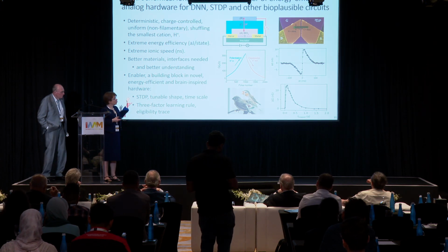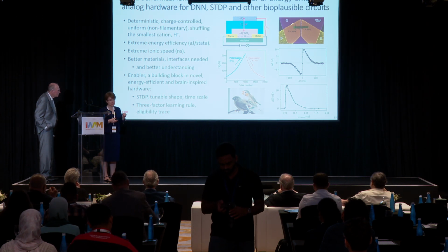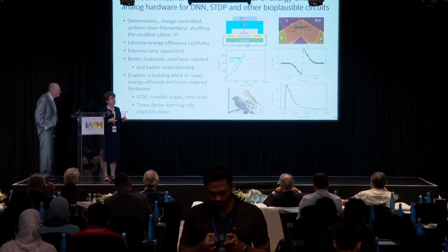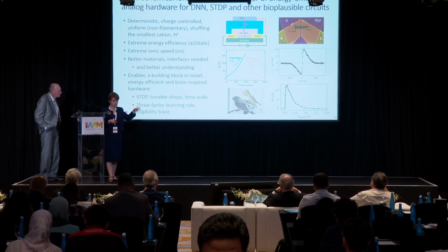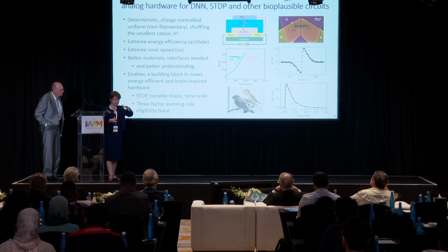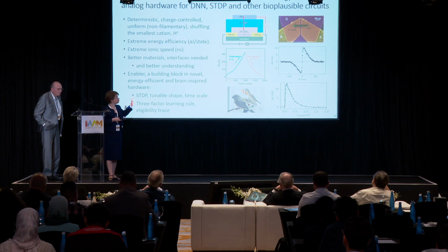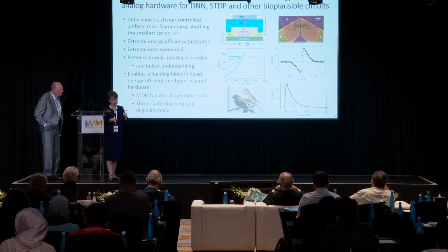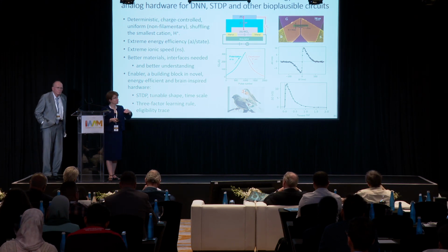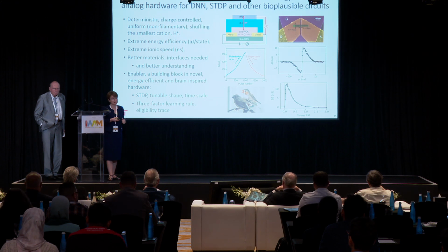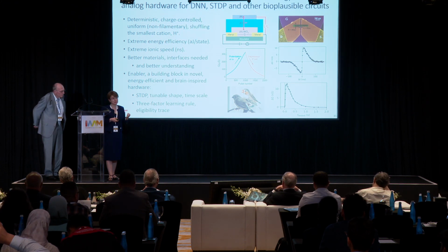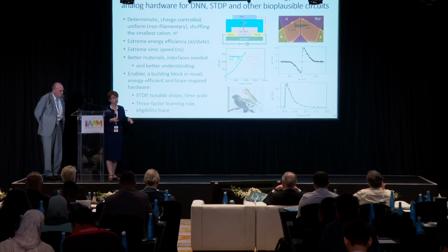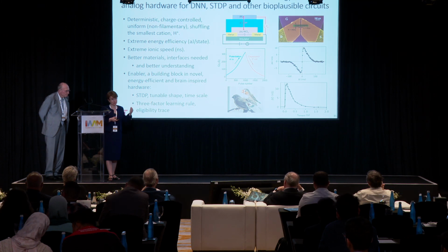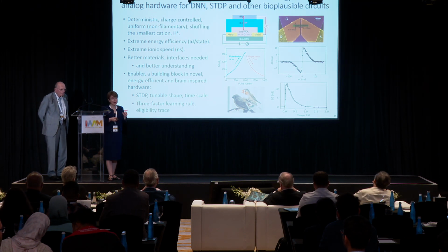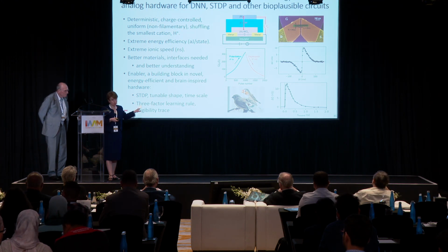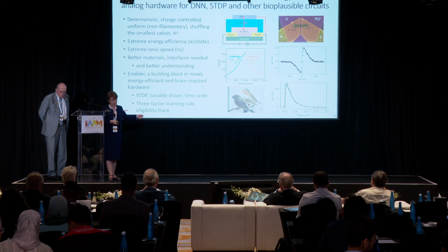Yes. With those nanoporous, disordered, low-density systems, indeed, you need the adsorbed OH layers at the least. In the proton conductivity field, this is typically done by controlling the humidity, showing that conductivity goes higher at higher humidities, and we do that separately for conductivity measurements. But with these devices, it's whatever is adsorbed from ambient. So ambient OH that's absorbed in this nanoporosity during preparation in the case of PSG, or just ambient exposure with the hafnia and zirconia layers, gives us some proton conductivity, but still very low, on the order of 10 to the minus 10, in fact, when we look at it without controlling humidity. That's why we need to go to very high fields to get reasonable speed out of them. So the role of OH and water is there, but for practicality of these devices, we don't increase humidity as we try to control the electronic conductivity.